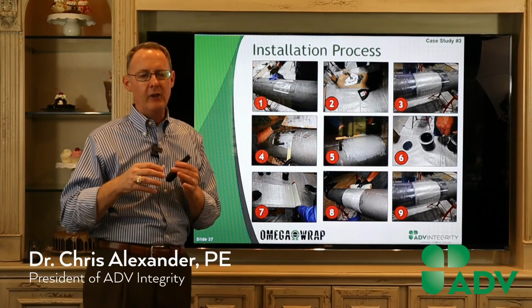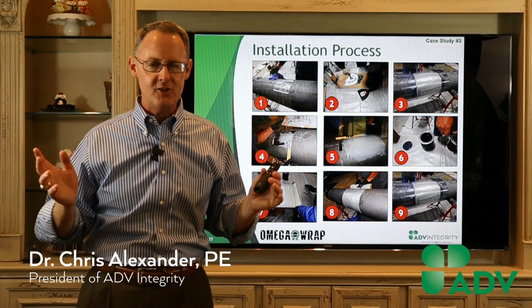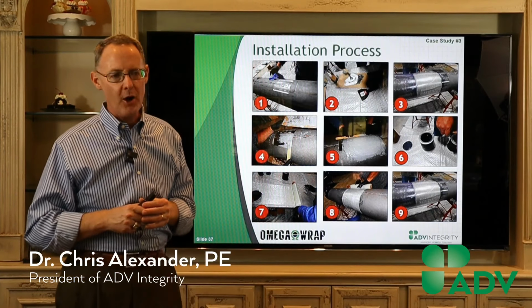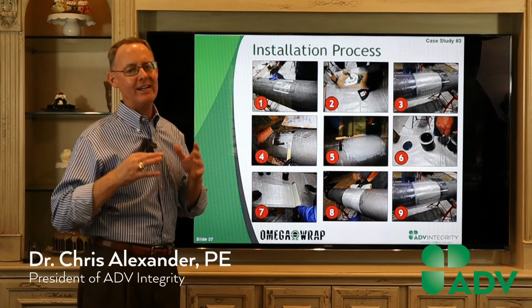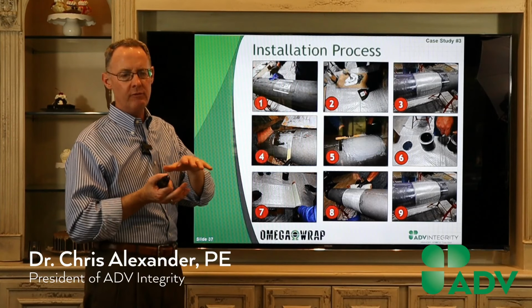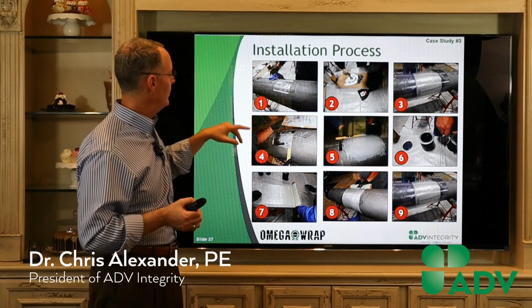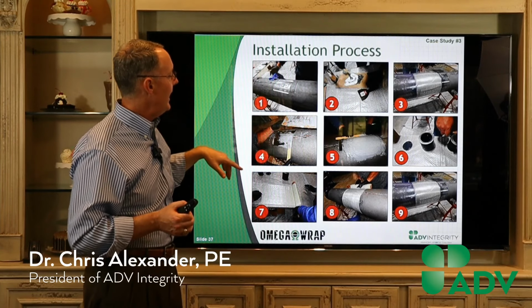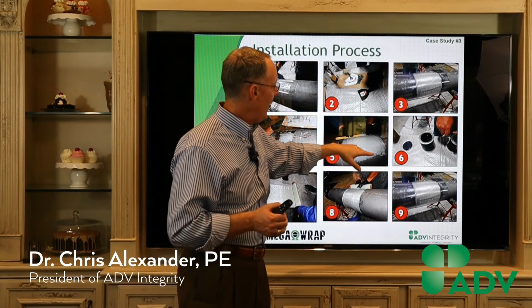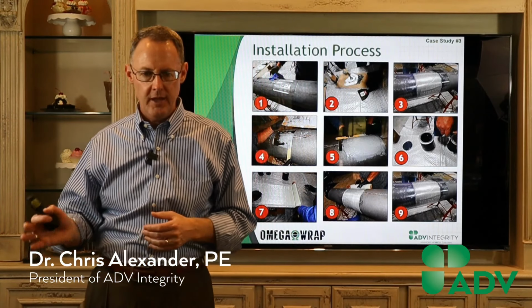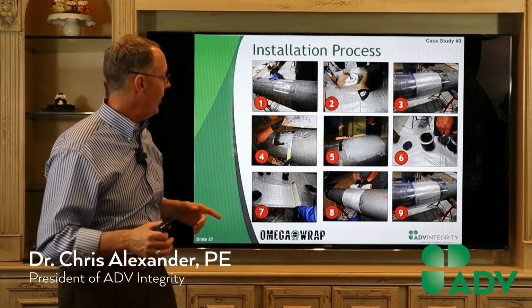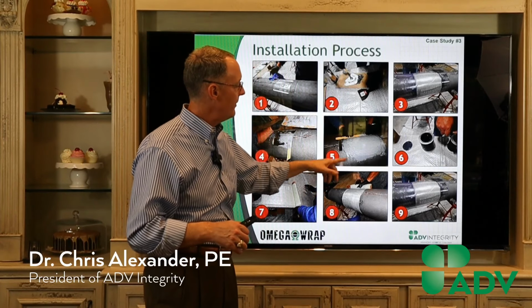It's a little bit like Bondo. I hate even saying that because you can go to High-Low or some auto parts store and get Bondo, but this is a high-tech Bondo that's got a very high level of compressibility. You mix it up, you put it in the corrosion area, and you see us smoothing it out. And then in step 6, we start saturating the cloth. And then once we saturate the cloth all the way down here in 8, you see us wrapping it around.